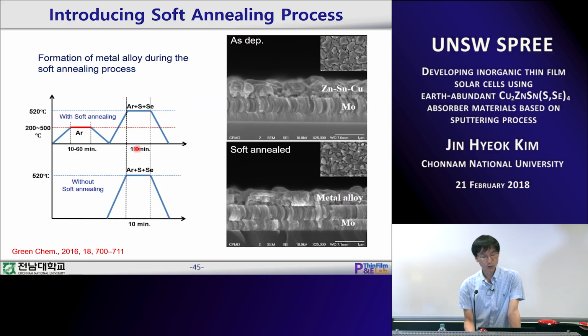Before this soft annealing process, we just annealed the sample directly to the desired annealing temperature, held the sample for a certain time, and cooled down to room temperature. But from the previous reports, we learned that it is better to introduce a soft annealing process to intermix the precursor layer to form alloy. That is a necessary process to avoid the loss of elements, mainly tin loss.